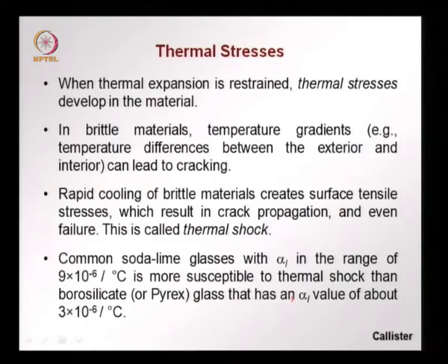Different types of glass react differently to thermal shock. Say when you have common glasses, soda lime glasses with a linear coefficient of expansion in the range of 9 times 10 to the power minus 6 per degree Celsius. This is more susceptible to thermal shock. So, this is a type of glass that I just mentioned. If you have it on the stove heating up, say anything that is being put in it, and then you transfer it to a very cold environment, or you pour ice water into it, then it could crack and break suddenly.